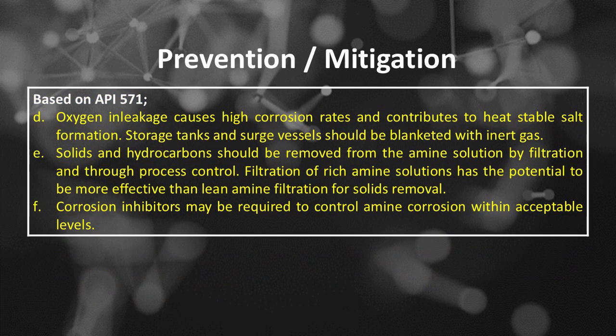Number D, oxygen in-leakage causes high corrosion rates and contributes to heat-stable salt formation. Storage tanks and surge vessels should be blanketed with inert gas. Number E, solids and hydrocarbons should be removed from the amine solution by filtration and through process control. Filtration of rich amine solutions has the potential to be more effective than lean amine filtration for solids removal. Number F, corrosion inhibitors may be required to control amine corrosion within acceptable levels.